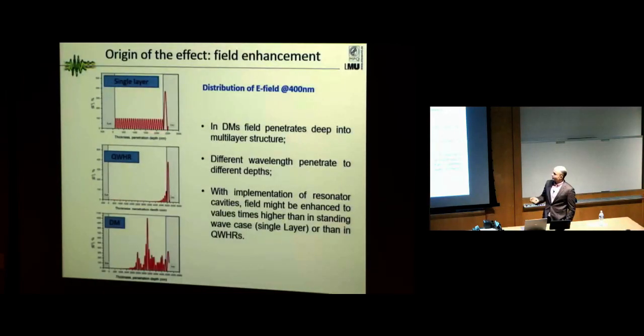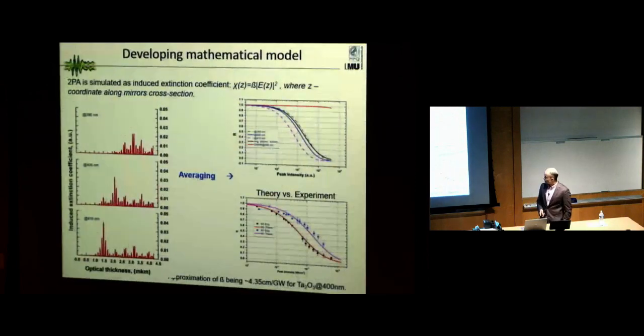Here you can see how the electric field looks for different structures. Here single layers, here we have a substrate, we have the incidence medium, and from this side our light is coming. It shows how the electric field looks inside the multilayer structure for a quarter wave stack, and how it looks for our dispersive mirror. For some certain frequency, because of the cavity, we have a very high peak of the electric field in our multilayer structure, and that explains why we observe this two-photon absorption.